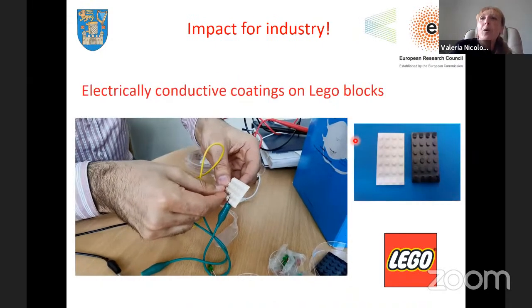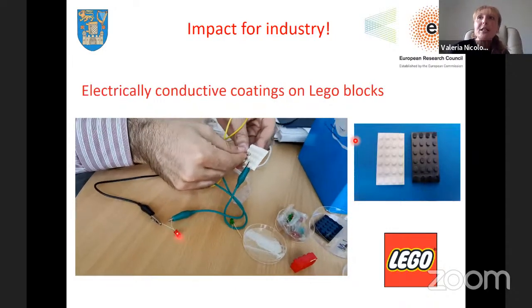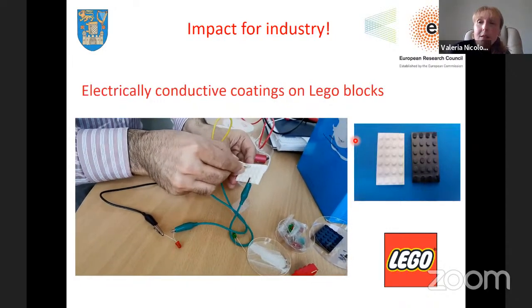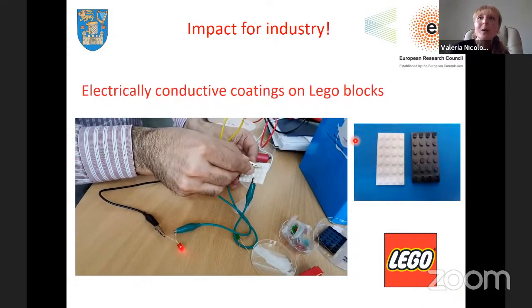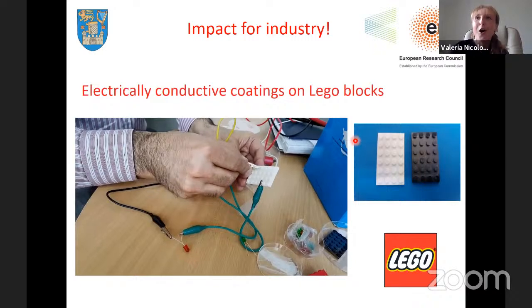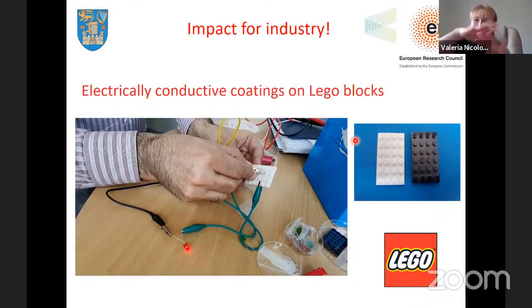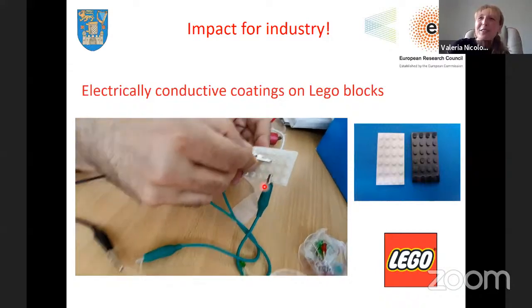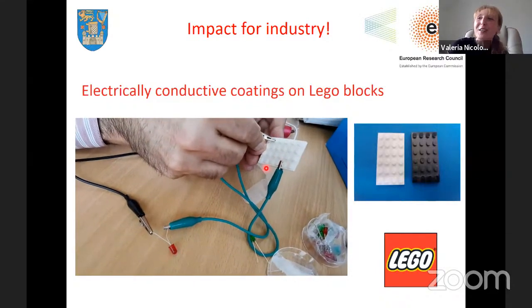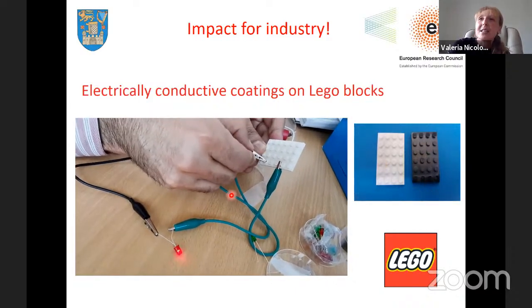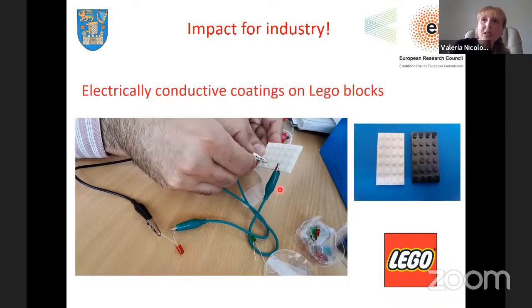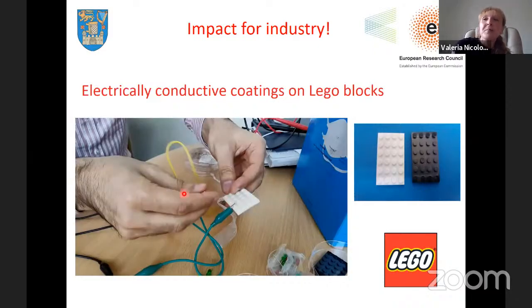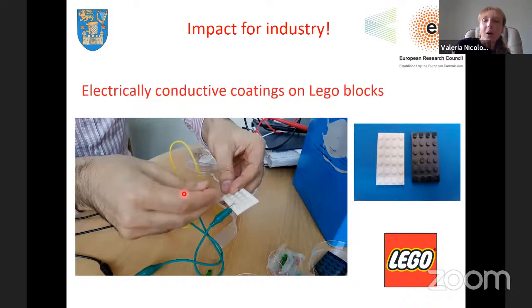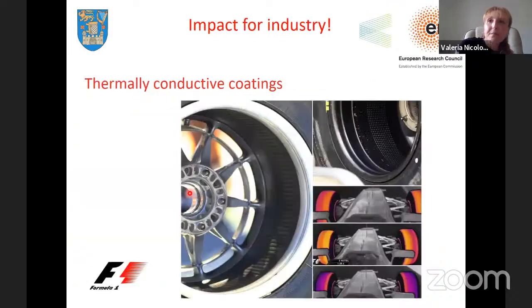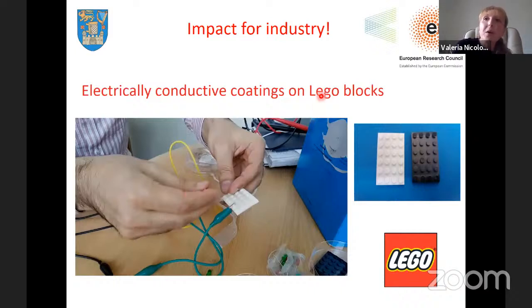Last but not least, we developed a conductive, fully transparent coating for Lego blocks. This is on a white one. I decided to show the white Lego block because if you get a horrible grayish, graphene-type color, if it is not perfectly conductive and transparent, you would actually change the color. And here it is on the black as well. So these are Lego blocks that have been coated with a transparent conductive material. And you can see, I'm going to play it again, hopefully, the conductive one doesn't play anymore, but you could have seen the LED lighting up when you were making the contact.